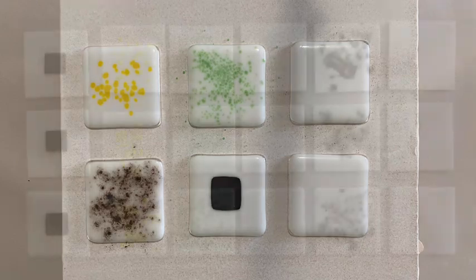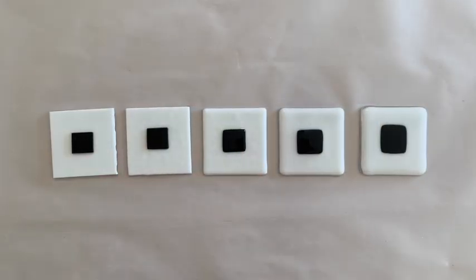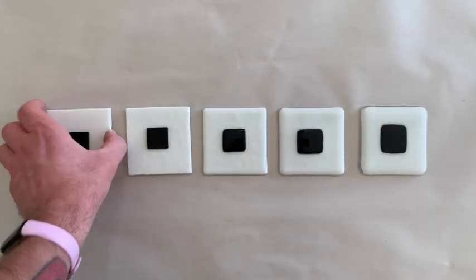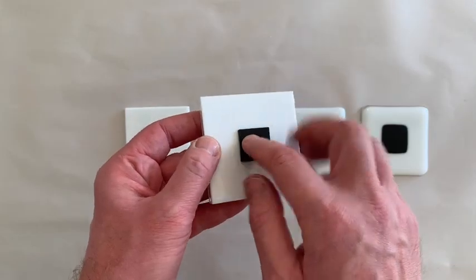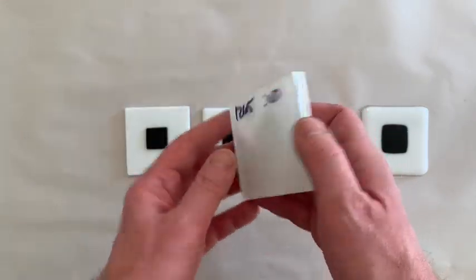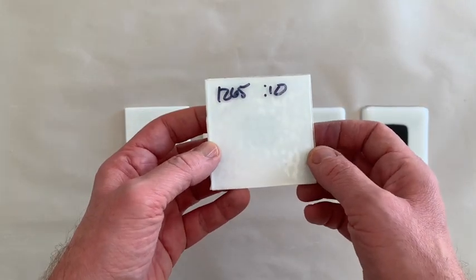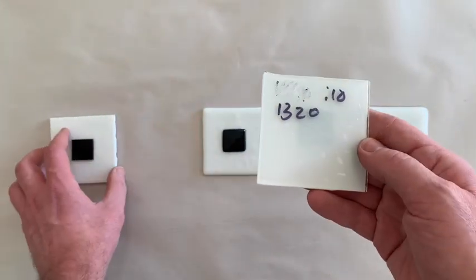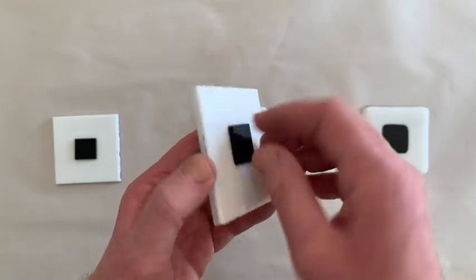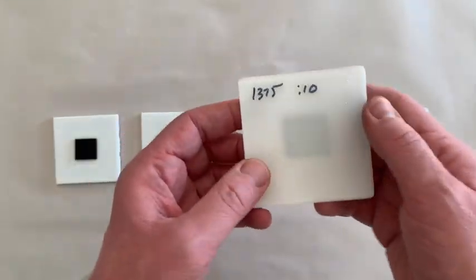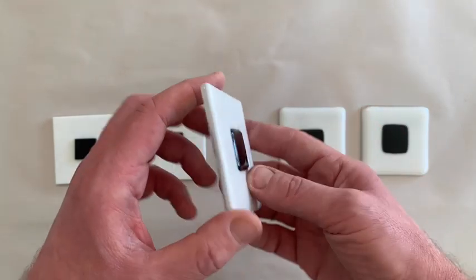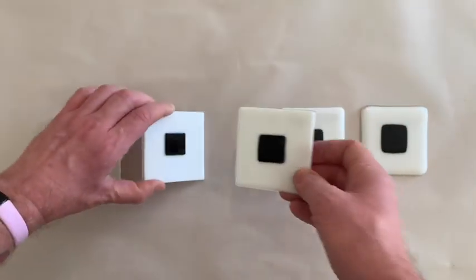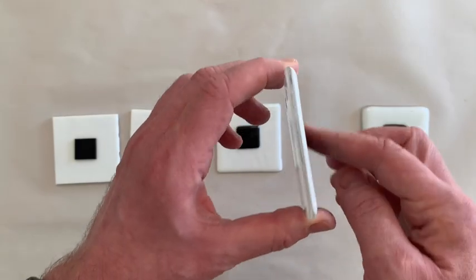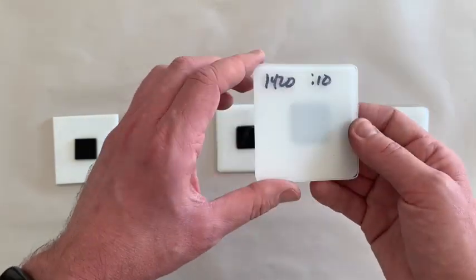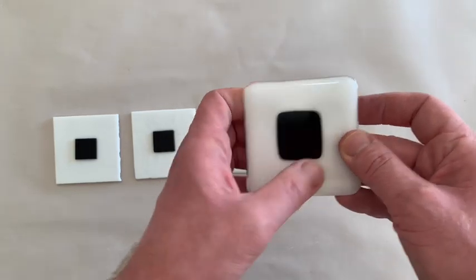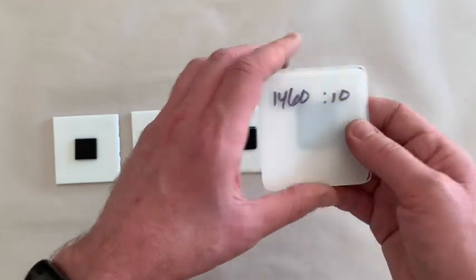Now let's take a look at each individual material. First, let's talk about the black sheet glass. The sample fired to 1265 degrees is tack fused, but the edges of the glass have not softened much. The sample fired at 1320 degrees Fahrenheit softened a bit more, but the black is still very pronounced. Notice the difference in the black square between 1320 and 1375 degrees Fahrenheit. At 1420 degrees Fahrenheit, the black glass is almost fully fused, but still slightly raised. At 1460, the black glass is fully fused flat into the white base piece.